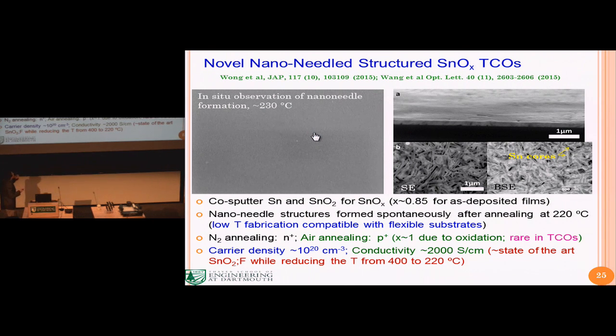The interesting structure is that when you do this co-deposition and annealing, you start to see some nanoneedles appearing. The left-hand side is a video; we'll show you the in situ formation observation a little bit later. But we also analyzed this photograph with backscatter mode of SEM. You can see some bright lines over here. Those are essentially the tin cores because they signify heavier atoms. So this is like a core-shell nanoneedle structure.